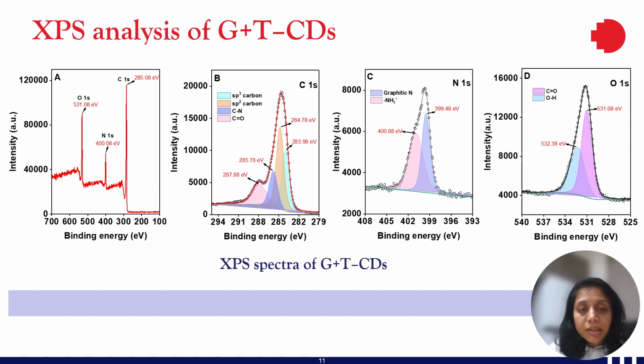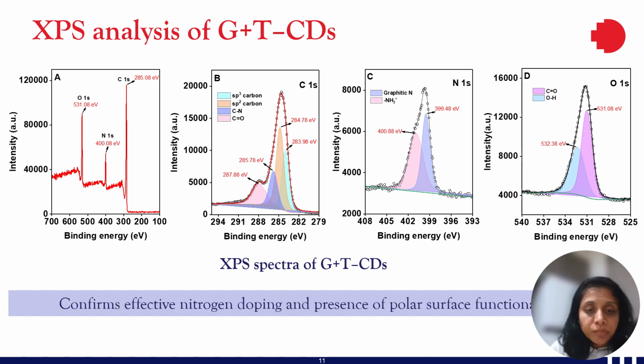The N1s analysis showed that there are 2 kinds of nitrogen corresponding to graphitic nitrogen and the protonated nitrogen. And the O1s level analysis showed 2 kinds of oxygen, probably originating from the surface hydroxyl oxygen groups and carbonyl oxygen, which is in agreement with the FTIR results. So the XPS analysis confirmed the effective nitrogen doping and presence of polar surface functional groups.